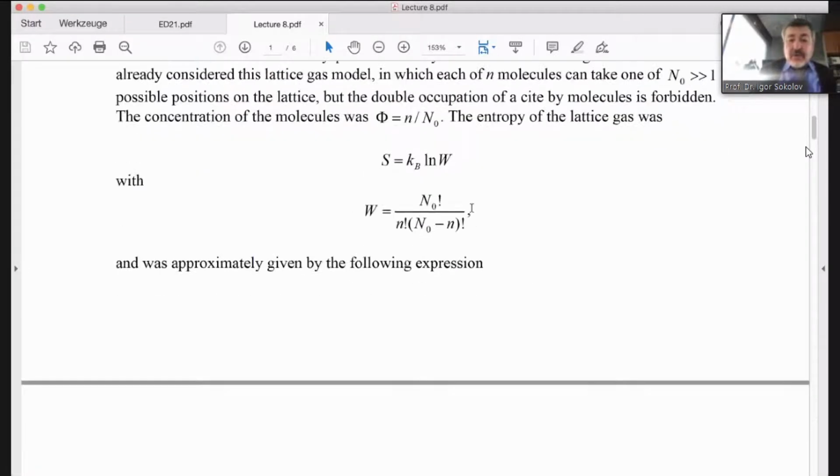Now, the entropy of your system, or the number of configurations, the number of arrangements of atoms in your system, is exactly the same as in the lattice gas. Because what I did up to now is simply renaming. What I called occupied was gold, is gold, and what I called empty is now copper.